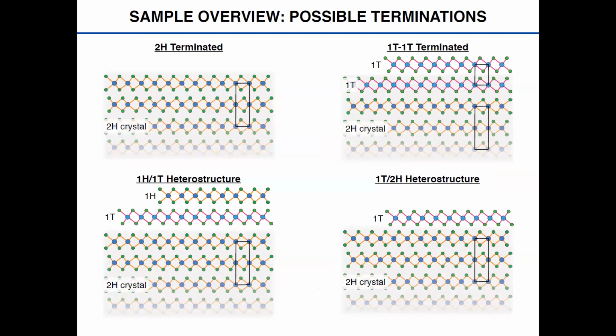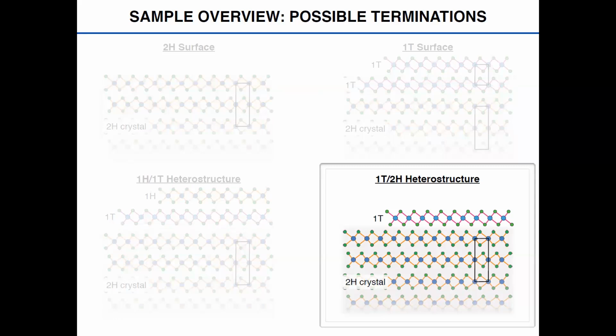Therefore, we understand that we have these 4 different possible terminations in our sample, depending on how the surface is terminated. So the simplest case would be 2H terminated. That is in theory the crystal we want. And then you have this 1T terminated, meaning that the first 2 layers would be 1T. And then these are the most interesting cases, in my opinion. First, the 1H/1T heterostructure, so you have an H layer on top of a T layer, and then the 2H crystal. And the one I'm going to talk about today is this 1T2H heterostructure, so you have a 1T layer on top of the 2H crystal.